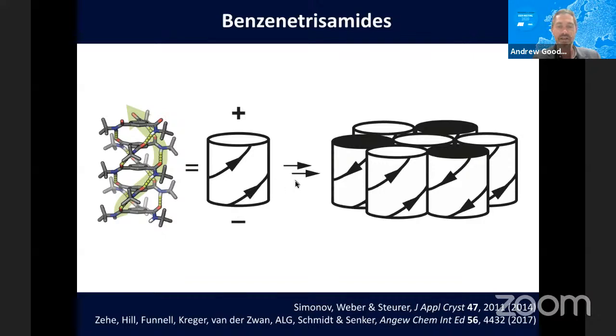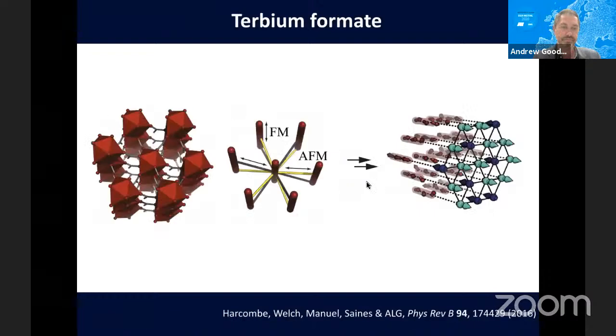And as they aggregate to form their own crystals, those columns pack as if on a triangular lattice in the same way that hard spaghetti would pack. But of course, because each individual strand has its own dipole, neighboring strands try and point in opposite directions. And this ends up giving rise to a complex state. I'll show you a picture of what this looks like in just a moment. But what's important here is this mixture of up and down; the domain size of these particular polarizations actually affects their ability to nucleate those plastic crystals.